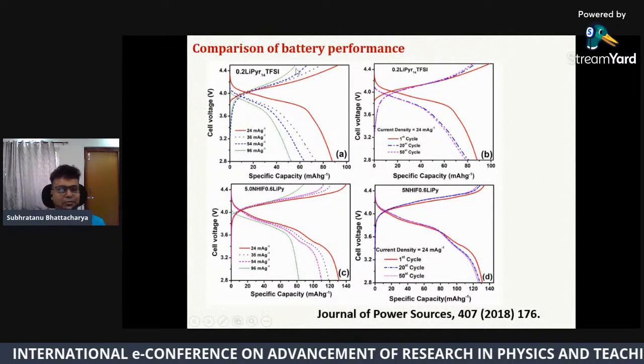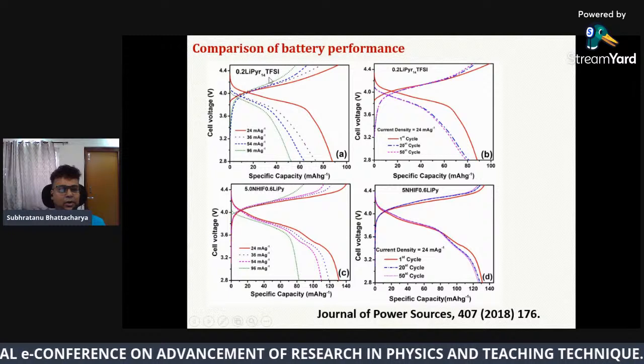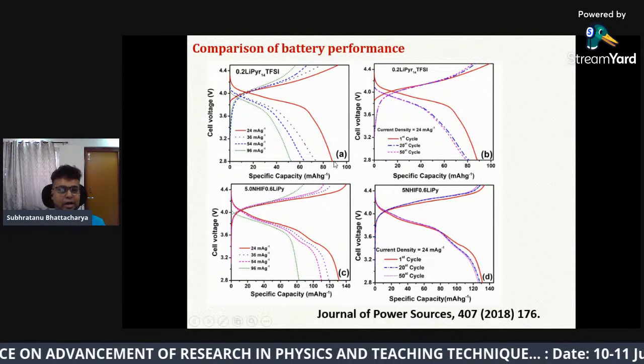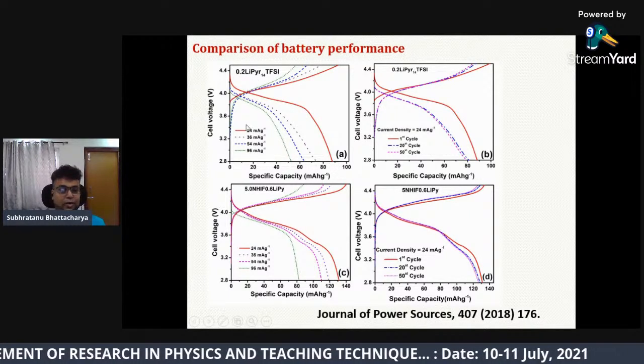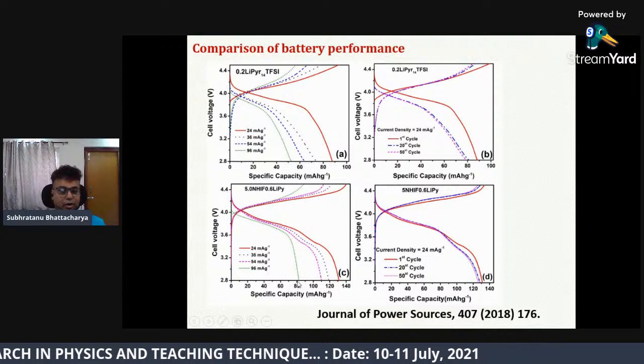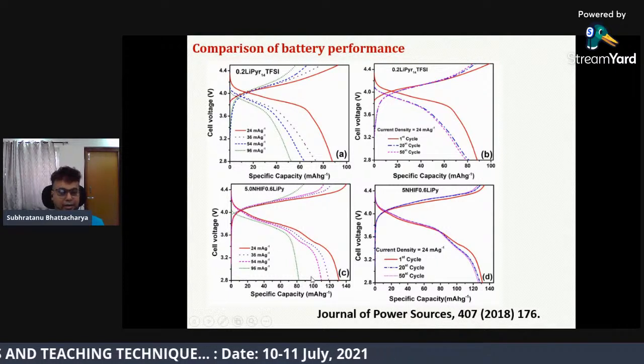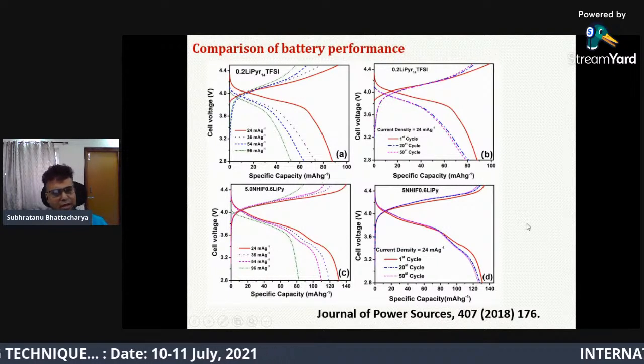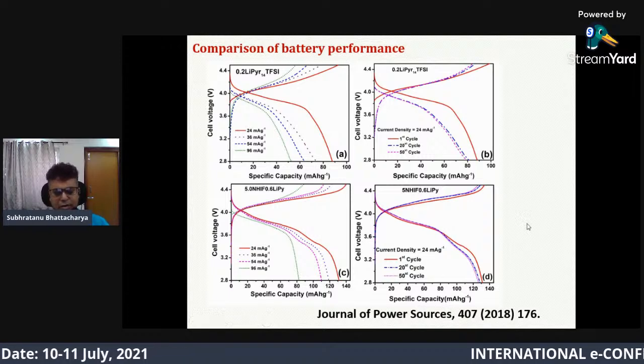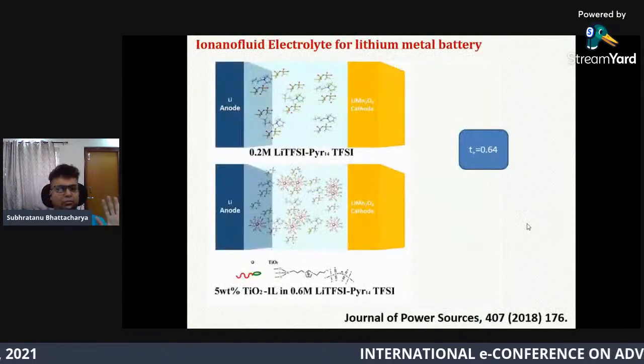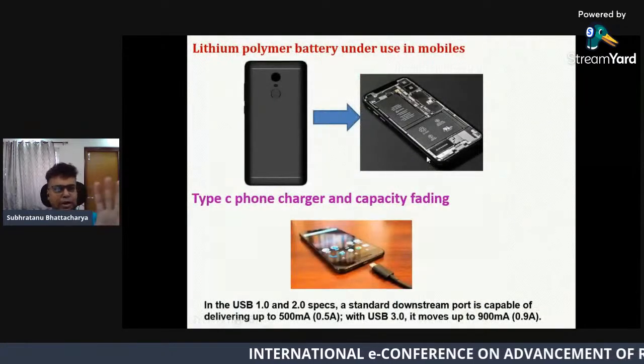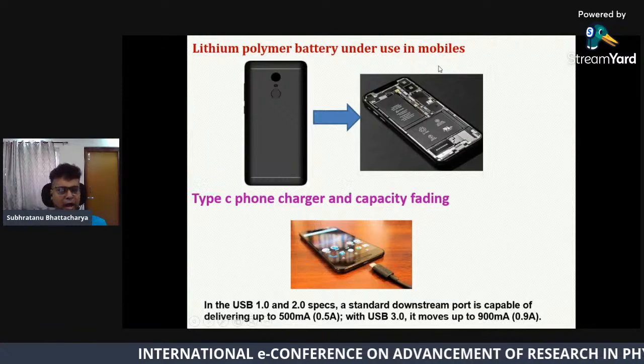which is actually achieved for a normal ionic liquid based battery at fast discharge at very small current. We get it at 4 times higher current density. So in that way we prepared something which I am now coming to, the lithium polymer battery used nowadays.